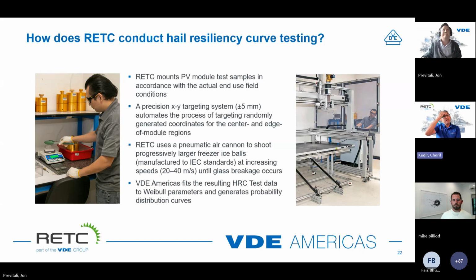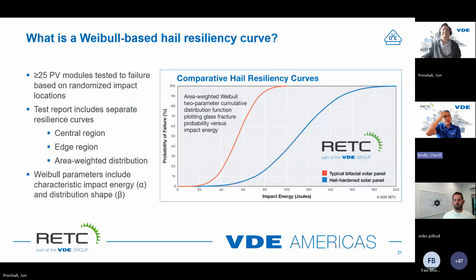So yeah, and I think one thing that's really important to note here, if you can go to the previous slide, JP, that I'd like to explain further is when we perform IEC type testing or UL or ASTM or FM type testing, where there's a table and you take a module and you randomly select certain locations and then you impact it, you have a limited number of opportunities to break that module, and when it breaks, you don't really have a statistical representation of what could happen in the field.